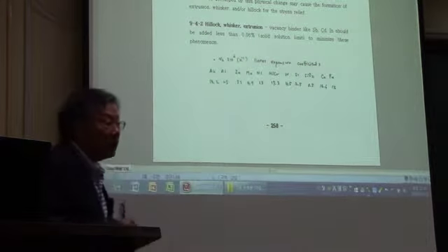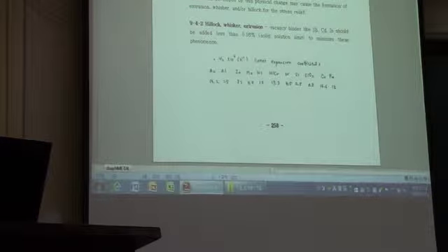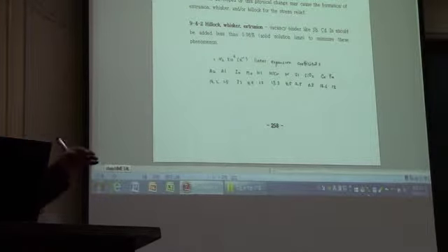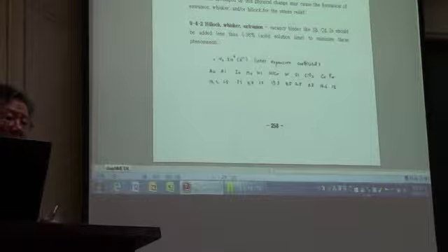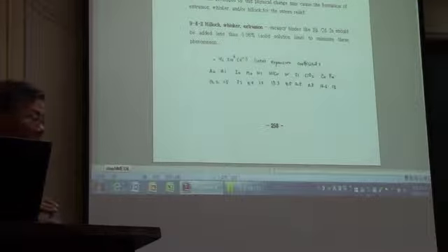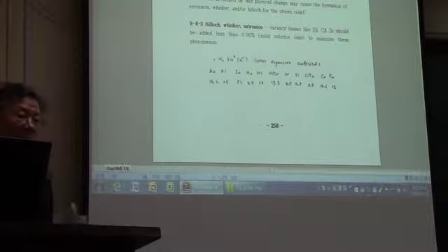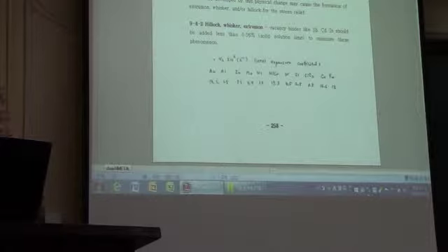So there's an enormous difference in the linear expansion coefficient, which means if you do thermal cycles, then the metal lines which are deposited on top of the silicon will expand, while the silicon substrate does not, so that we are going to have a mechanical